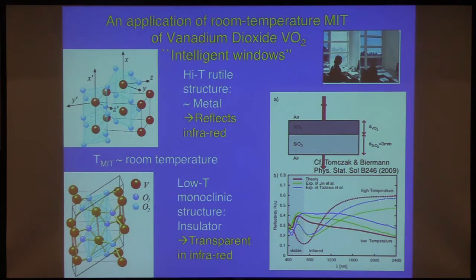Okay, so these metal insulator transitions are not only interesting to theorists, but they're actually also interesting for practical applications. This is another of the vanadium oxides, vanadium dioxide, and this one has the good taste of having a metal insulator transition just at about room temperature, at about 20 Celsius, so that you can actually switch it from being metallic above 20 C to an insulator below, and you can actually use it to coat windows that would let the infrared come in when it's cold outside and not let it in when it's hot outside. So people call these intelligent windows.